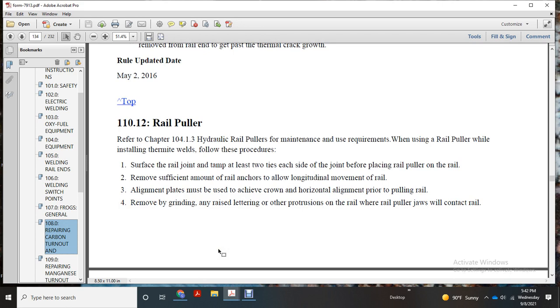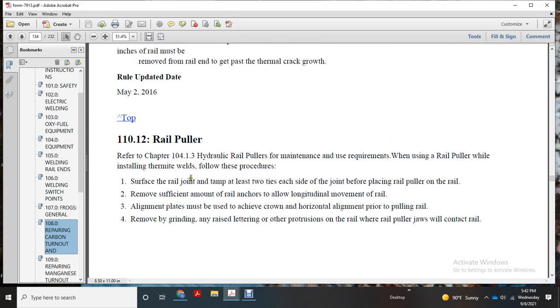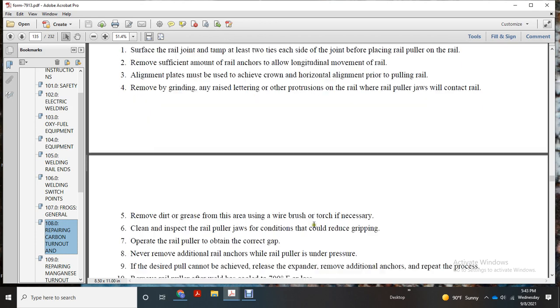Rail puller. Refer to chapter 104.13, hydraulic rail pullers for maintenance use requirements. When using the rail puller while installing thermite welds, follow these procedures. Surface the rail joint and tamp at least 2 ties on each side of the joint before placing the rail puller on the rail. Remove a sufficient amount of rail anchors to allow longitudinal movement of the rail, tie plate, and line. Make sure to achieve the correct horizontal alignment prior to pulling the rail. Remove by grinding, any raised lettering, and other protrusions on the rail where the rail puller jaws will contact the rail.